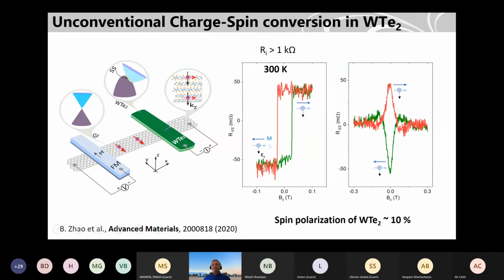You also see the spin valves when you switch the magnetization of this ferromagnet. And when you do a Hanle measurement with a perpendicular magnetic field, you see this Hanle spin precession signal for both parallel and anti-parallel configurations. The green is the anti-parallel, meaning the ferromagnet is in the opposite direction. From this measurement, we estimate the spin polarization to be around 10% for tungsten telluride, because we know the spin polarization of this ferromagnet.